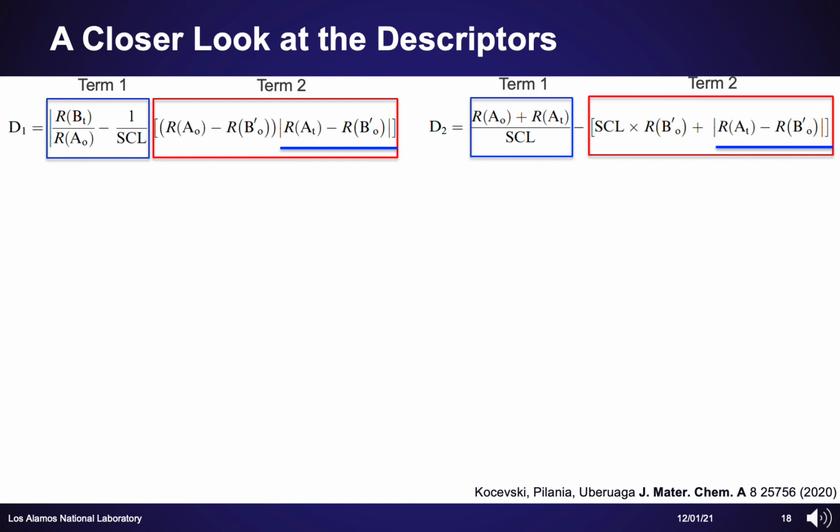It is also interesting to note that these terms share a common expression underlined with a blue line, which essentially captures relative local strain effects caused by forming a double spinel by combining two single spinels, one normal and one inverse. The role of the first term is a bit more difficult to comprehend just by a visual inspection alone.